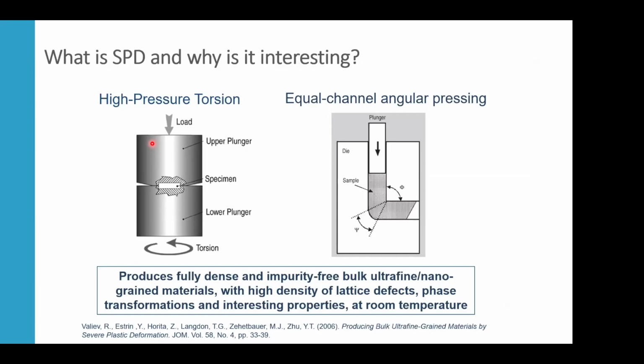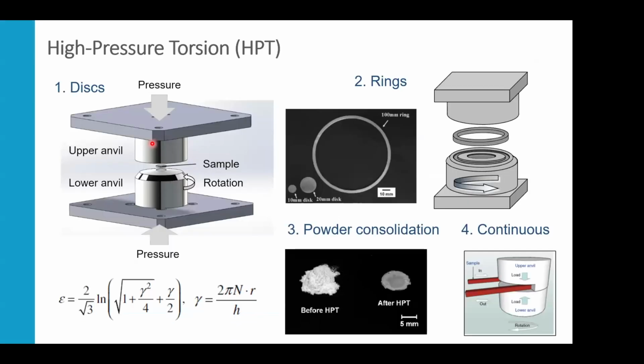And one of the positive aspects is that we can get very high density, no porosity, in a relatively easy way. We don't need to use any special atmosphere or vacuum or increased temperatures. So usually the cost is just driven by the energy input to the hydraulic press and the torsion system. And it can be done in a wide variety of materials, as I will show you later. We can mix very effectively even metals with very different melting points or low diffusivity. And that's also a very interesting aspect, because we can, for example, consolidate metal alloys or other crystalline materials from elemental powders. And we can achieve a very nice distribution of powders and second phase particles, for example. And as I will mention a little bit later, phase transformations under the high pressure can be stable even after we remove the pressure. So these are more or less the background of the field of high pressure torsion.